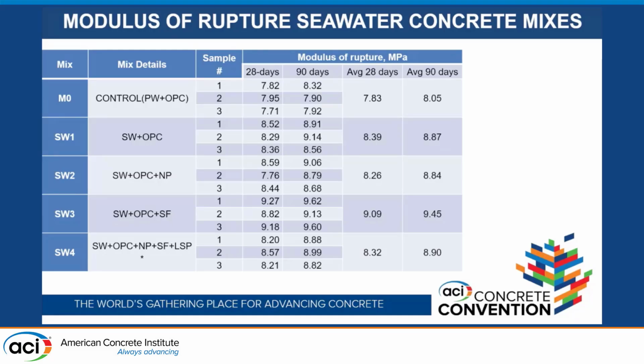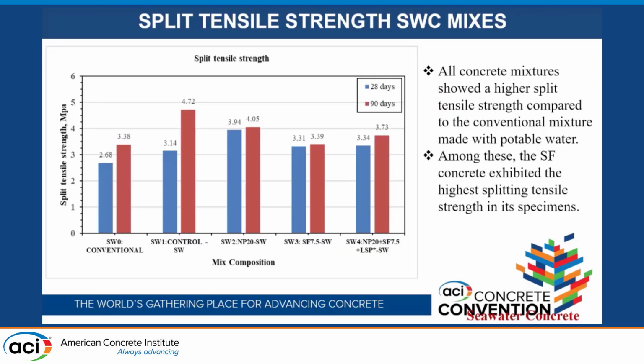Then with respect to the modulus of rupture, you can see that it was 7.8 for the normal control concrete, and for all other concrete mixes with seawater, it was slightly higher than the normal concrete mix. With the split tensile strength also, you can see higher split tensile strength compared to the conventional mixture made with the potable water. And among these, the silica fume-based seawater concrete exhibited the highest splitting tensile strength in its specimen.